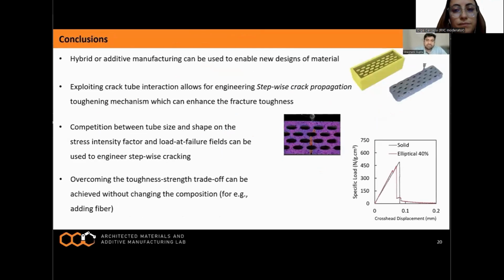In conclusion, we showed that hybrid or additive manufacturing can be used in a variety of ways to architect material. However, further work on scaling up is necessary. We also learned that toughening mechanism inspired from bone can enhance the fracture toughness of brittle cementitious material up to 5.6 times. The stepwise toughening mechanism can be further engineered by the competition between the tube size and shape on the failure stress intensity factor and load-at-failure.